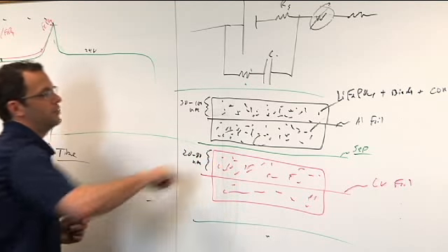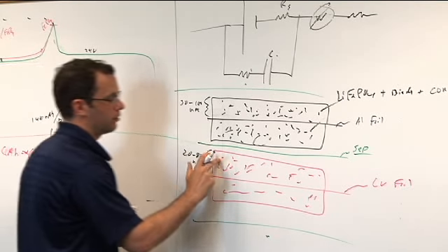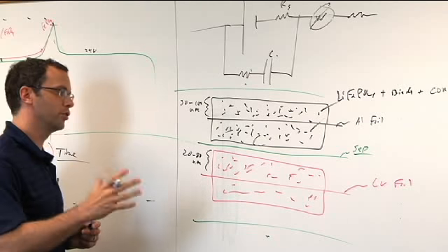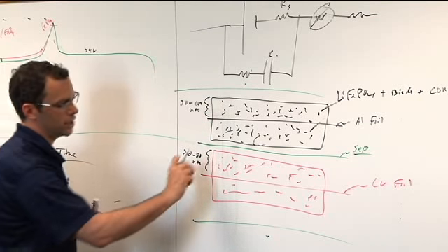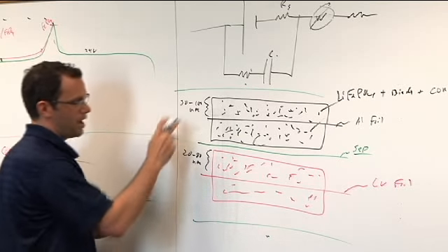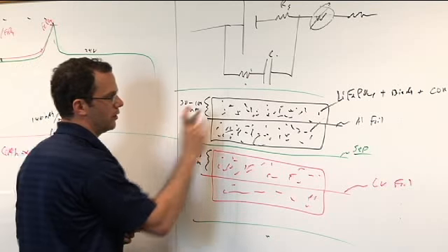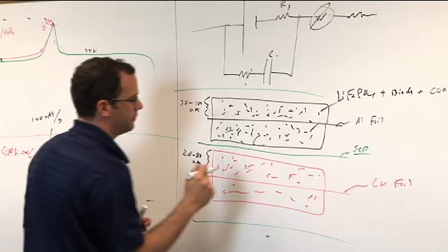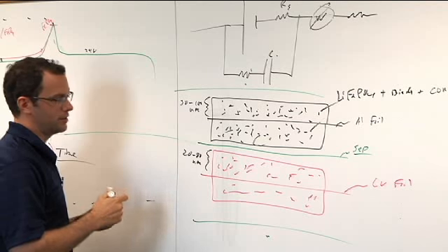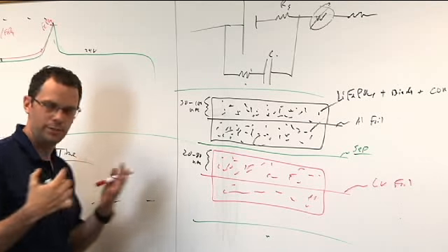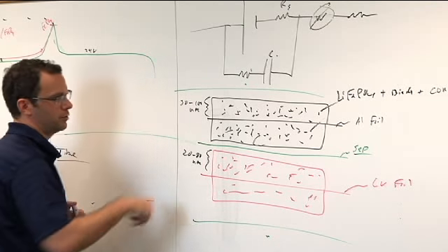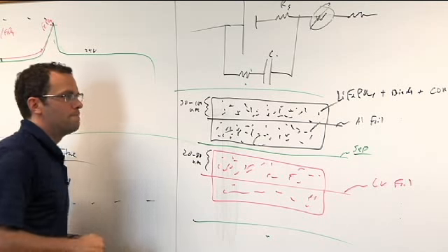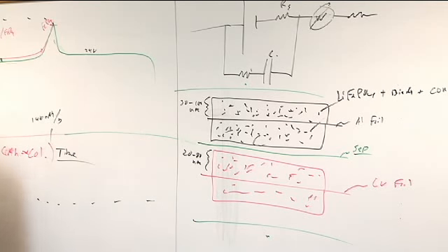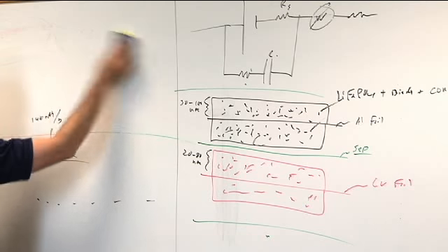The specific capacity of graphite turns out that it can hold more lithium per unit mass than most cathodes, so you actually need a little bit less. So if I have a 30 or a 40 or a 50 micron thick lithium iron phosphate, I probably need something that's a little bit less thick for my anode, and density plays into that too, and there's some trade-offs, but in general it's a bit thinner. Okay, so now I'm going to erase this now, and now I'm going to talk about a real live cell. Okay, and this is where things are going to become more interesting.